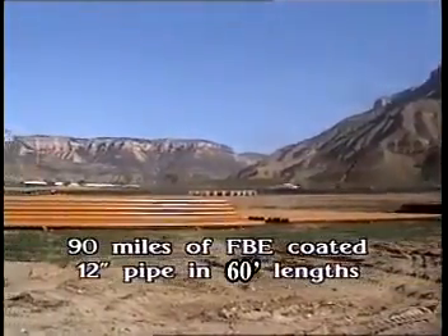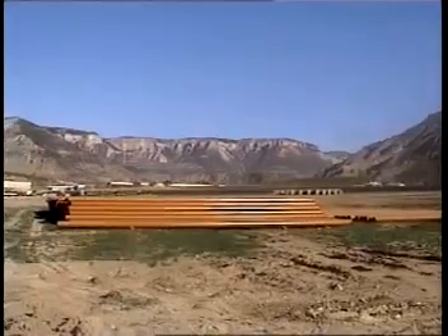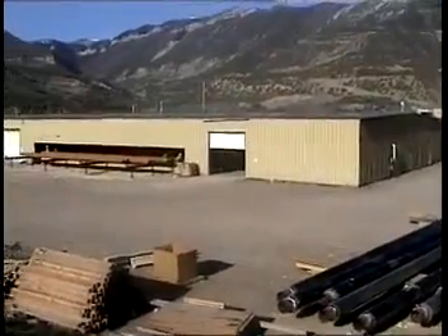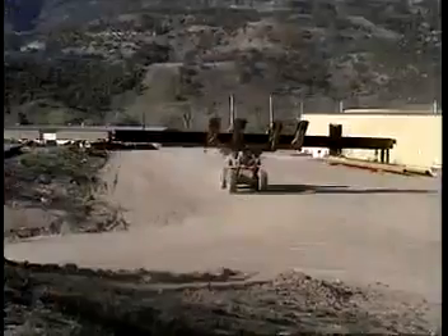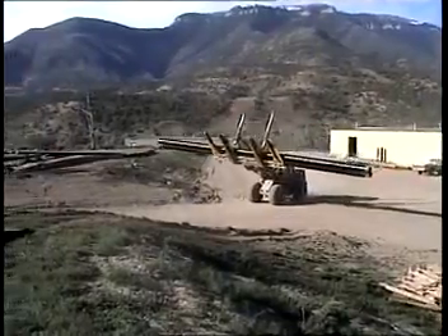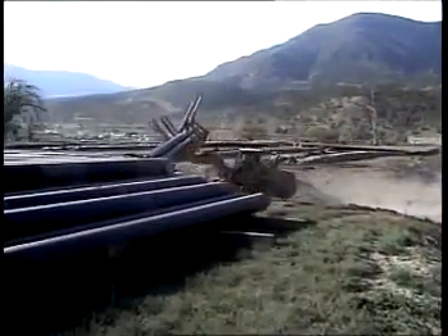The second carries the recycled hot water back to the mining location. Perma Pipe also performed a thermal and pressure stress analysis of the entire pipeline. Perma Pipe was supplied 60-foot lengths. All pipe was 12-inch diameter, .406 wall, coated with 30 mils of Napgard Gold fusion bond epoxy. This coating was chosen for its ability to withstand the continuous operating temperature of 225 degrees Fahrenheit.